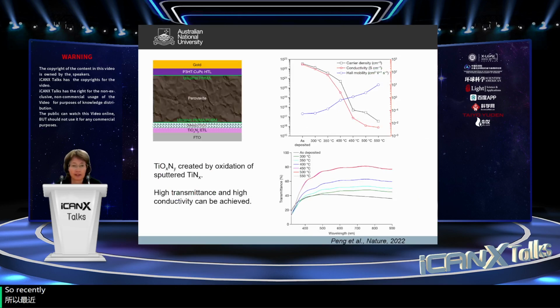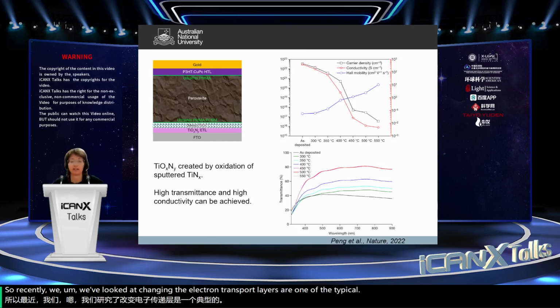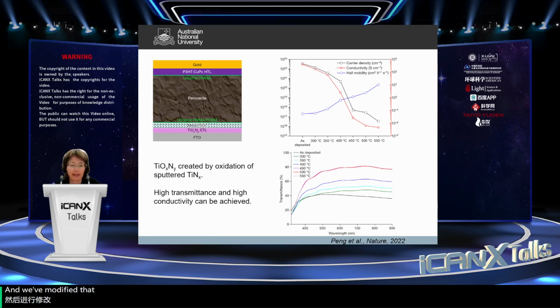So recently we've looked at changing the electron transport layers. One of the typical electron transport layers is titanium dioxide, and we've modified that to create a titanium oxynitride. One of the limitations of the titanium dioxide is its conduction is not as high as it could be. So titanium nitride, of course, itself is very conducting, but also not transparent. So by using titanium oxynitride, you can get a film that's highly transparent, but also highly conducting by getting that mixture and also by treating it at around 450 degrees.